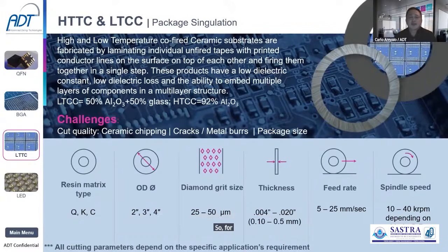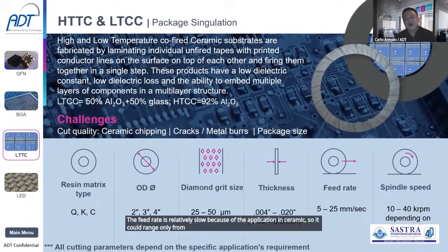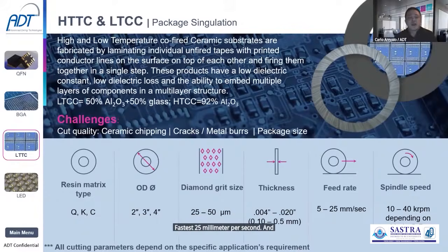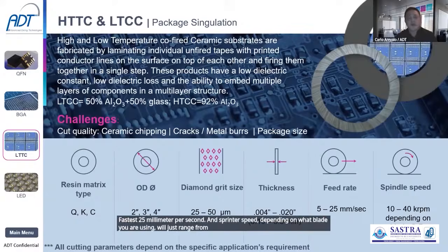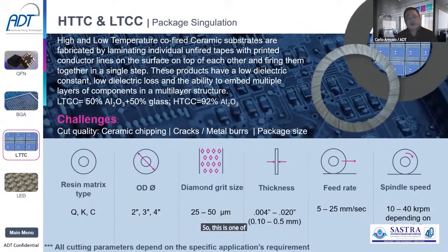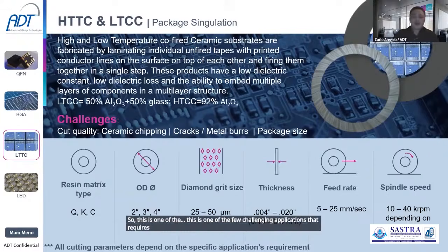So for this particular hard material, the recommendation or the process would normally be using a resin blade because it's a soft blade. ADT has a few models like the Q, K, and C matrix. The OD sizes range from 2, 3, or 4 inches. Diamond grit sizes are from 25 to 50. Thickness ranges from 100 to 500 micron. The feed rate is relatively slow because of the application in ceramic, so it could range only from 5 to as fast as 25 millimeter per second. And spindle speed, depending on what blade you are using, will just range from 10 to 40K. So this is one of the few challenging applications that requires blades, ceramic materials.